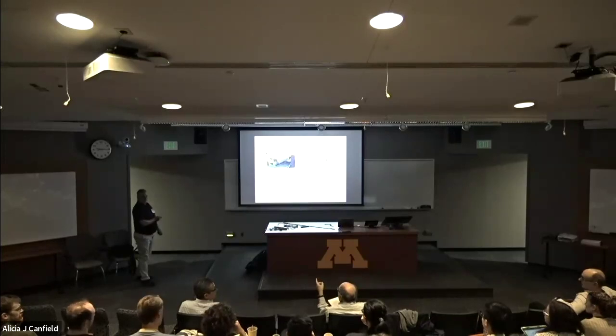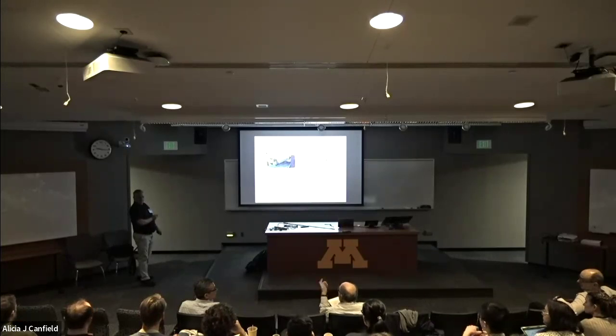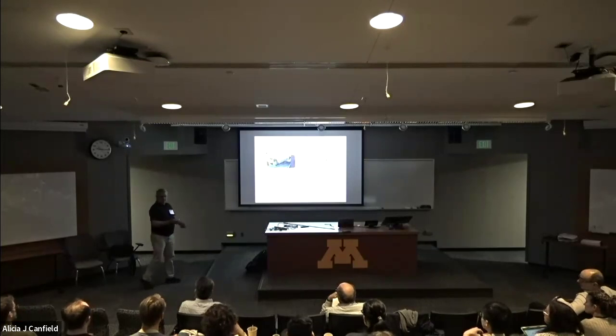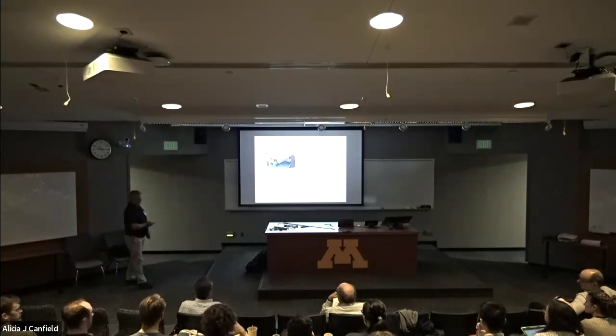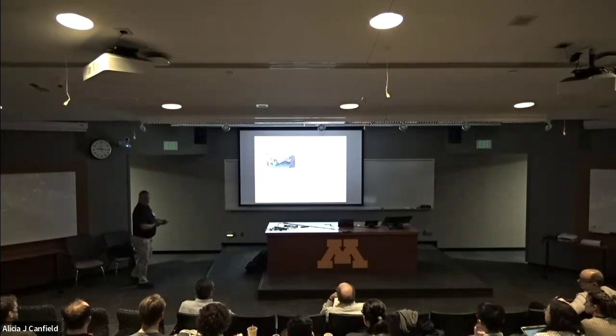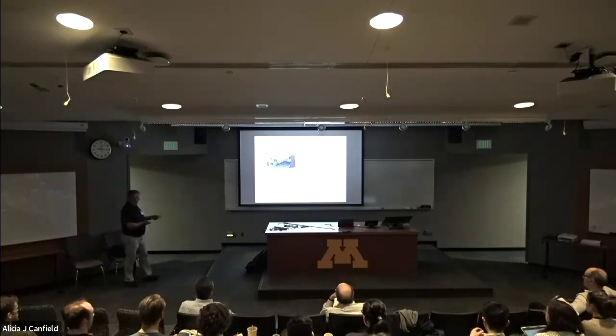Indeed, but you see enormously high conductivity both at low temperature in the defect scattering regime and at high temperature where it's electron-phonon dominated. That's correct. So it has a very weak electron-phonon coupling in that sense. And very weak defect scattering in this sense. And very weak defect scattering, and we're going to quantify that right now.